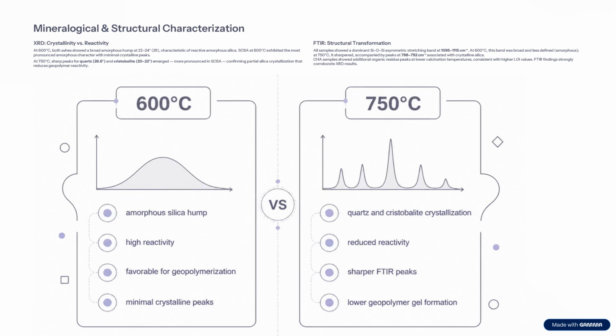For FTIR, all samples show a dominant Si-O asymmetric stretching mode at 1095 to 1115. At 600 centigrade, the band was broad and less defined. At 750 centigrade, it was sharp, combined with peaks at 788 to 792 associated with crystalline silica. CHA samples show additional organic residual peaks at lower calcination temperature, consistent with higher LOI values. FTIR findings strongly correspond to the XRD results.